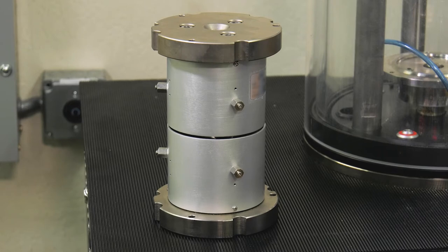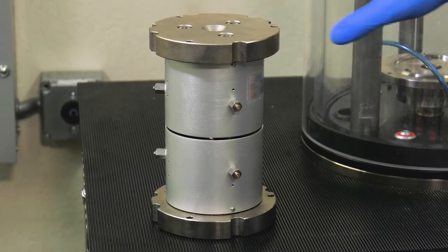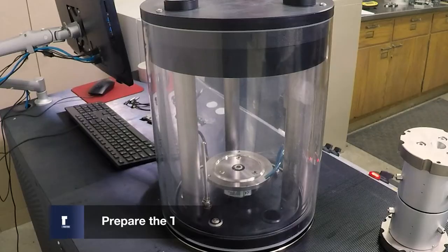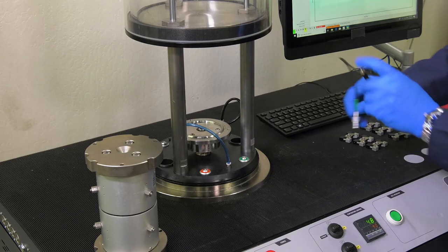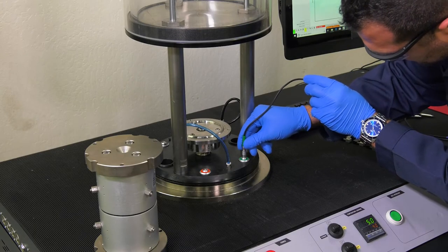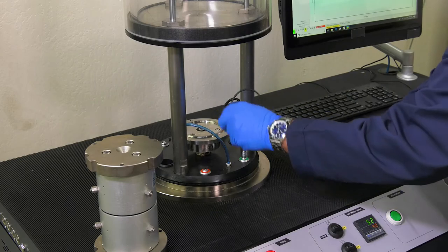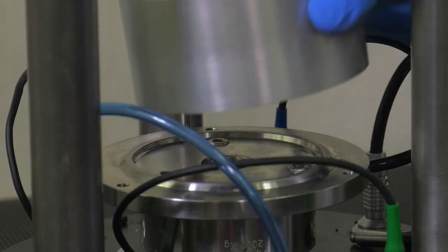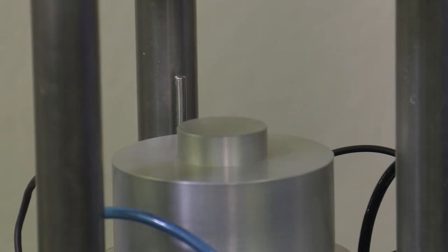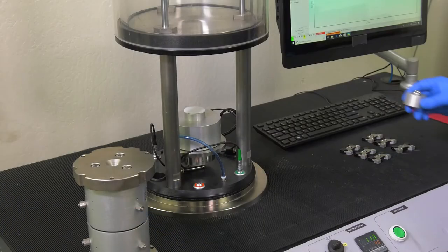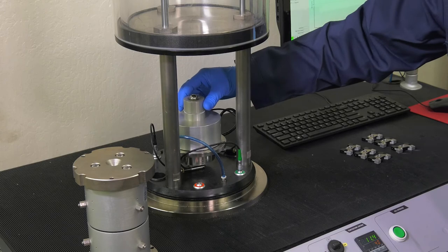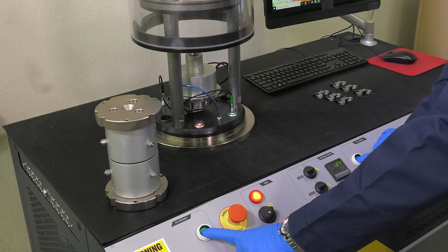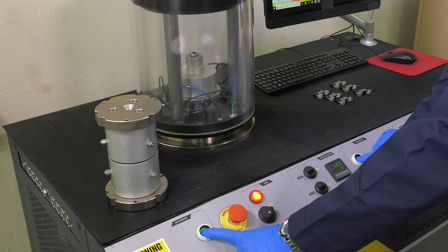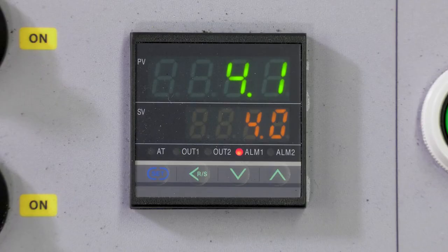Verify the calibration of the AMPT using a proving ring before beginning this test. Prepare the AMPT conditioning chamber. Open the AMPT conditioning chamber and install the LVDT sensors and fixtures required for small-scale specimen testing. Place the bottom platen, PTFE sheets, and the top platen with steel ball in the chamber. Close the chamber and set the temperature control to the desired testing temperature. Allow the testing chamber to equilibrate for at least 1 hour at the testing temperature.